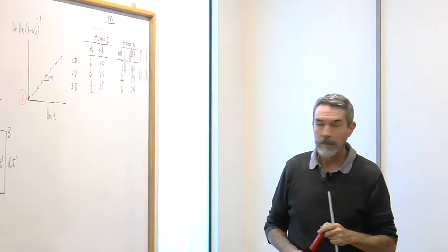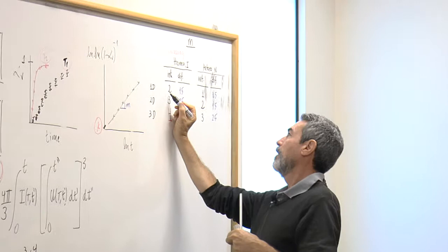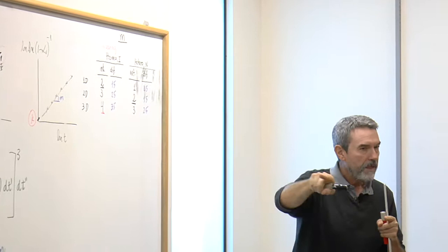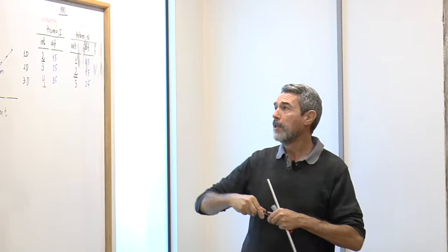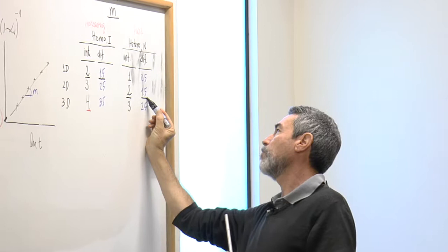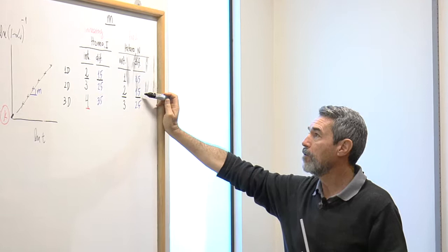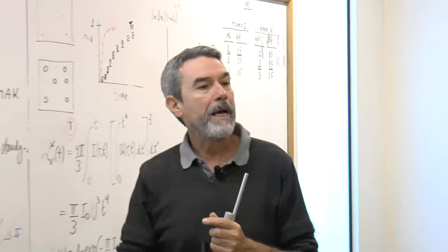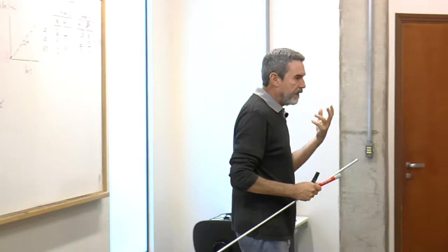There is a little bit of complication here. If M is equal to 2, you can have either internal nucleation of unidimensional crystals or surface nucleation and growth of circular crystals. Or you may have a situation where M is 1.5, and you can have diffusion controlled growth of unidimensional crystals with homogeneous nucleation, or diffusion controlled growth of two-dimensional crystals in heterogeneous nucleation. So these cases have to be resolved by detailed microscopy work. If you look in transmitted light, reflected light, you can find out the shape of your crystals, and then you know which case you're working with. See?